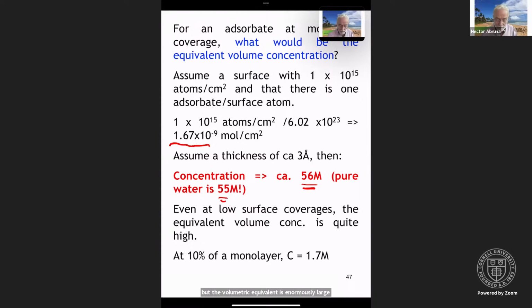And so, for example, even at low surface coverages, if I told you, do you think a 10% monolayer is concentrated or not? I'm pretty sure that a high percentage of the current 230 participants now would say, probably not so strong. And you would be incorrect. 10% of a monolayer is of the order of almost 2 molar. And I don't think anybody thinks that 2 molar is a dilute concentration. Why do I mention this? Because if you have adsorbed intermediates in any mechanistic pathway, then the contribution to the overall rate is going to be very significant.